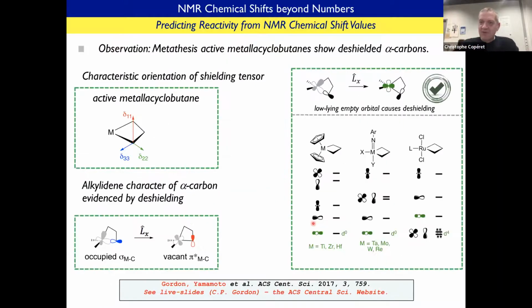And based on that, we actually measured and calculated this chemical shift tensor, and we can see that the principal component of the chemical shift tensor, the most deshielded component, delta 1,1, is oriented again perpendicular to the ring of the metallacyclobutane in the case of the active metallacycle. And based on calculation, we can trace it back to this metal-carbon sigma bond, which means that there must be a low-lying empty orbital to be able to couple with that metal sigma bond